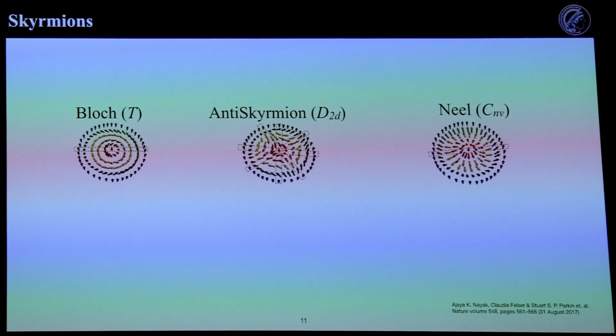The other thing that happens here is that you get actually two other skyrmions out of the system that are very close in symmetry. It looks very similar to this, but just a bit rotated, and also this one, just a bit rotated. But another thing you get from this is that because of the symmetry relations, when you stabilize the skyrmion by DMI, you can never stabilize two distinct skyrmion classes in the same system, unless you really, really go a priori to engineer a system from the ground up. And in one material, it's not really possible to stabilize two types of skyrmions.